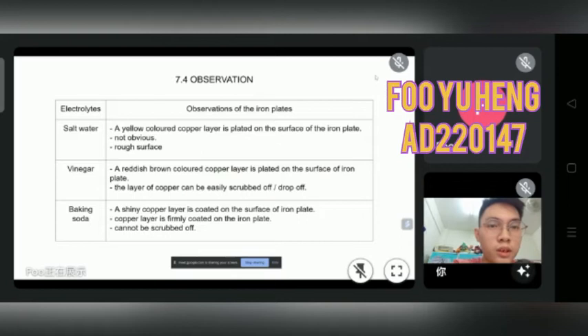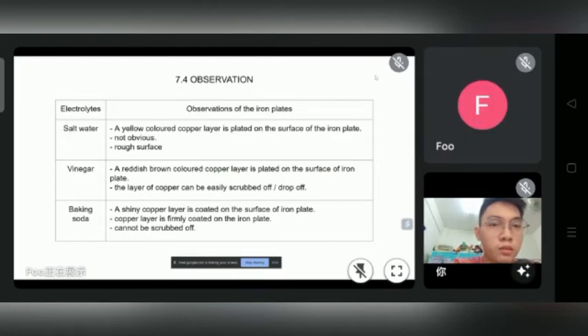In this experiment, we have used three types of electrolytes, which are salt water, vinegar, and baking soda. And all three types of electrolyte are successfully undergo electroplating process. And also, all iron plates are successfully coated with a layer of copper, but each of them have different kind of effect. So firstly, by using salt water as electrolyte, a yellow color copper layer is coated on the iron plate, but it is not obvious to see, and it also have a rough surface on the coated layer.